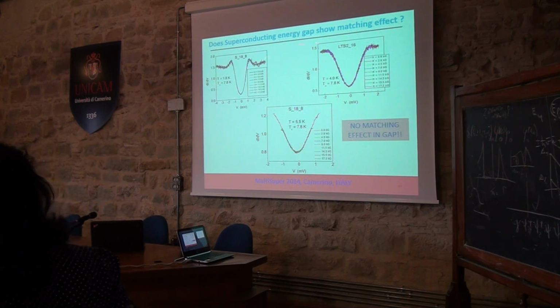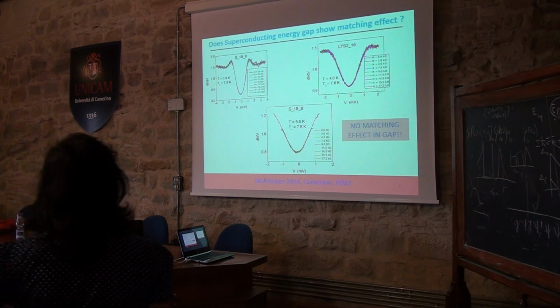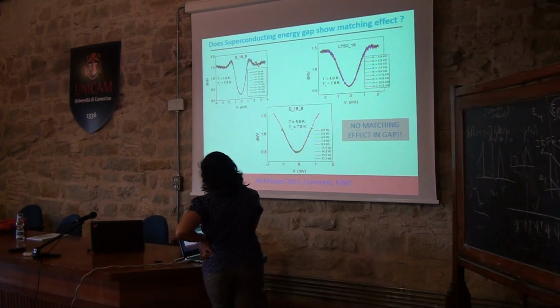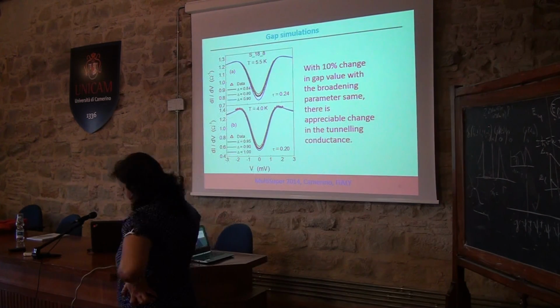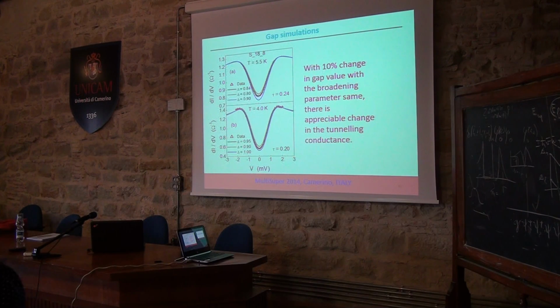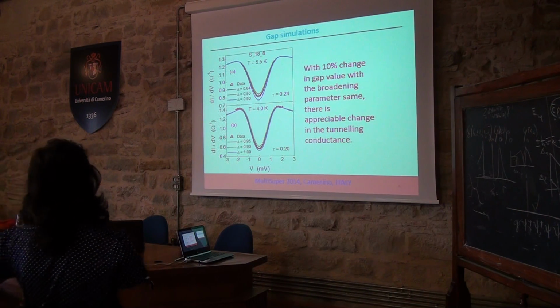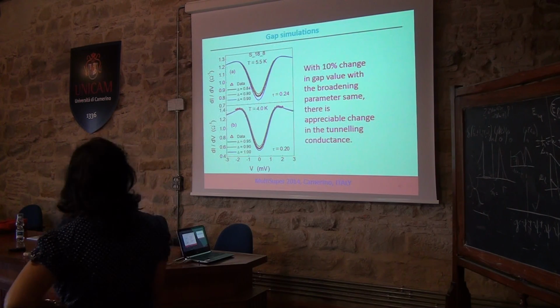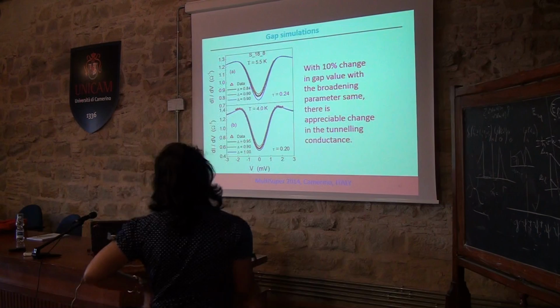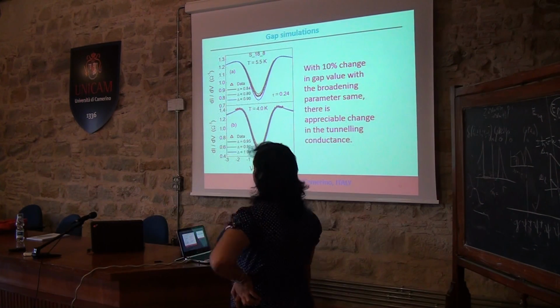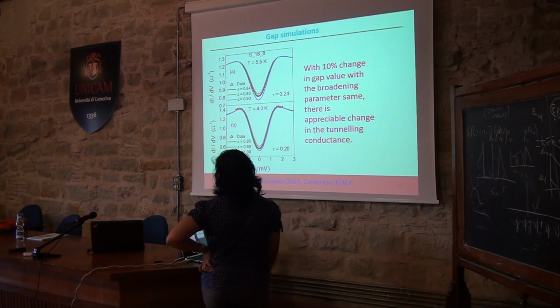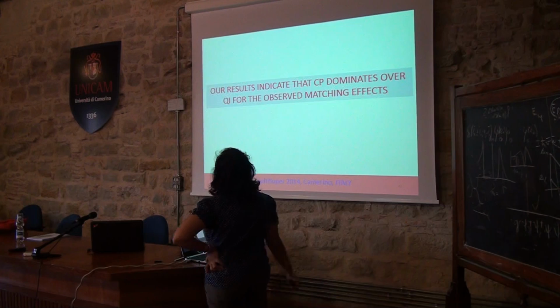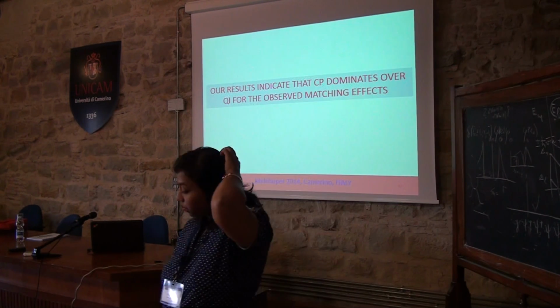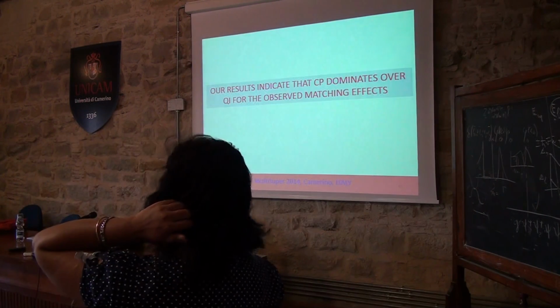What we see is that whatever temperature you measure, you don't see any matching effect in the superconducting energy gap. So the tunneling spectra really match one on top of the other. So there is no matching effect in the superconducting gap. We wanted to check whether this is within our resolution limit. So we changed the gap value, suppose by a 10% change, to see whether we can measure the difference in the tunneling signal, and we see that there should be a difference in the tunneling conductance, which was not observed in our experiments. This means that truly we are not seeing any oscillations in the superconducting energy gap. So our results indicate that commensurate pinning is the more dominant feature observed for these matching effects.